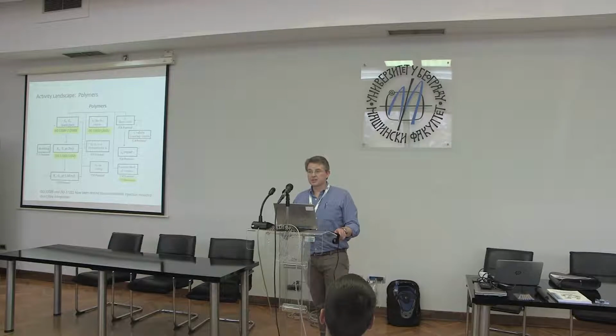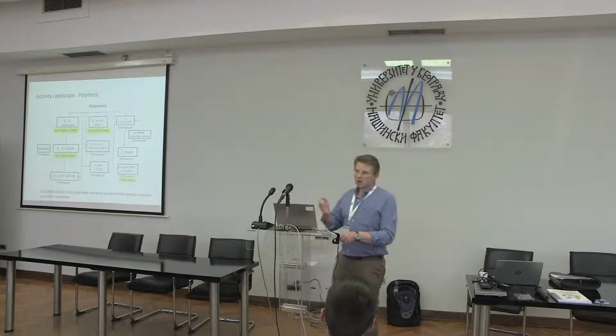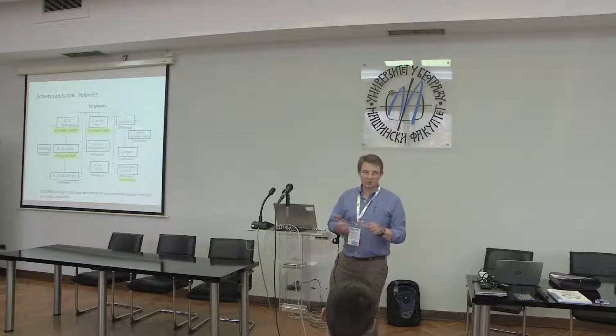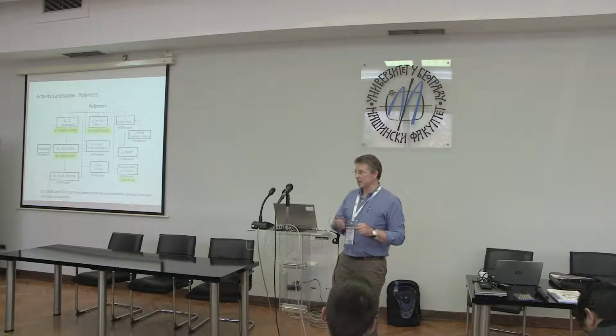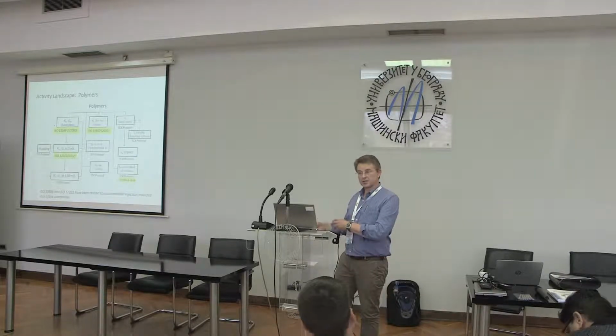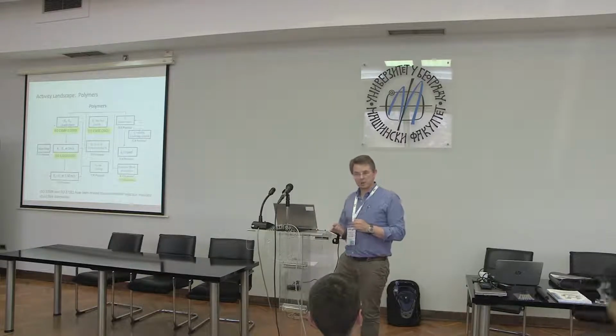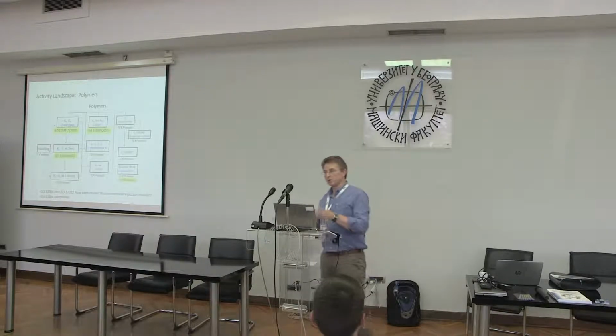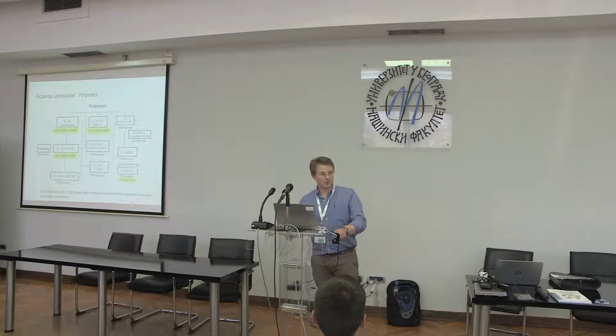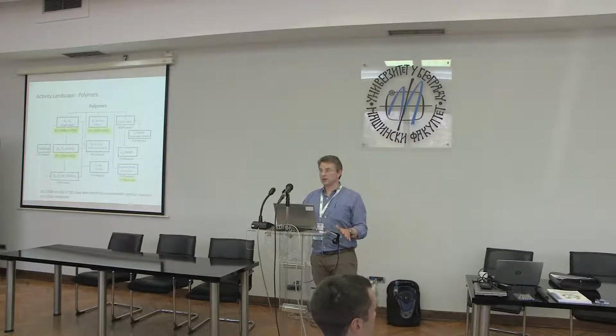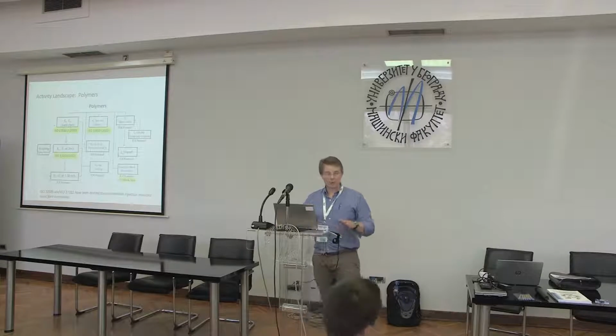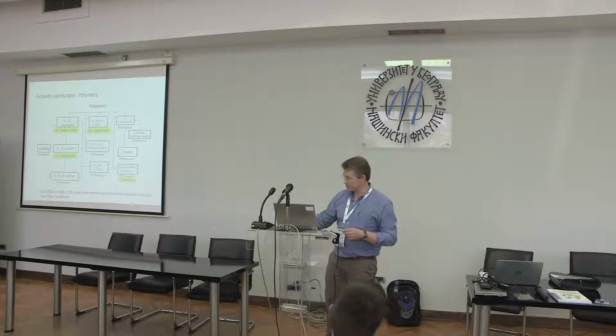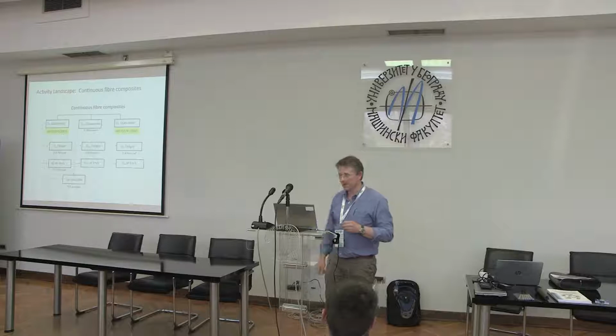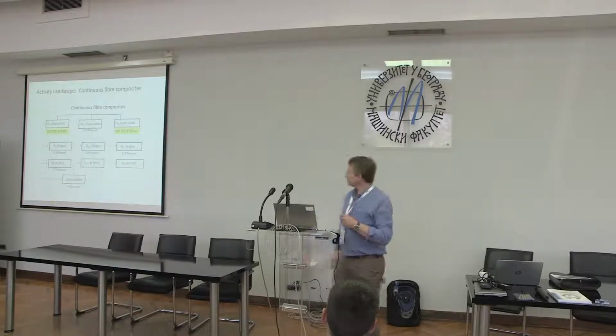So the idea is that sometimes if you can't apply LEFM to a polymer specimen and you want to avoid the complexities of J, sometimes you can use a cutting approach. With a cutting approach, you're removing a thin strip of the material and trying to determine the energy required to do that, and if you plastically correct that, you can end up with a term which we correlate to GC. So I'll say a little bit more about that later on.